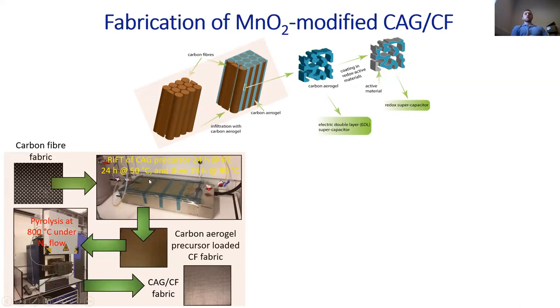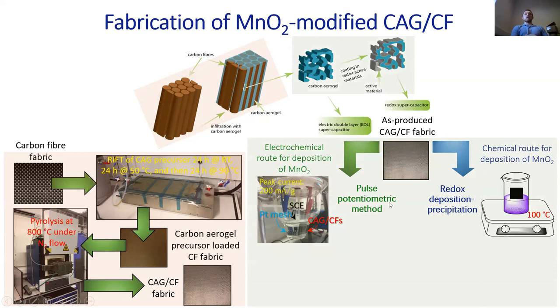After infusion, the organic sol undergoes different temperature steps for gelation and curing, which results in a solid piece of carbon fibers with the carbon aerogel precursor, which can be further pyrolyzed at high temperature, leading to carbonization of carbon aerogel in the inert gas, forming high surface area electrodes, which can be further used as the starting material for deposition of manganese oxide.